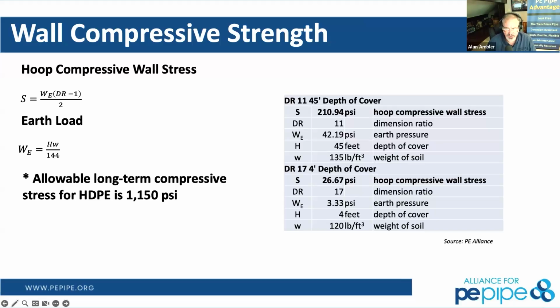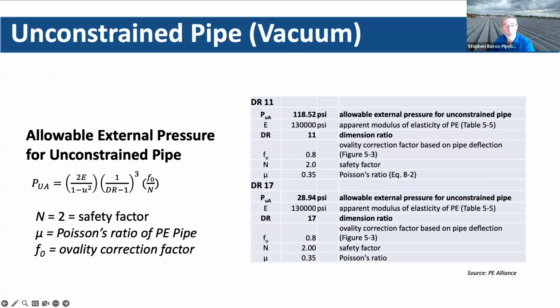Yes, Peter or Stephen? Yeah, Alan, just on that vacuum. That's a really good point, especially looking at force main design and things like that, which could go under vacuum if your vacuum relief valves fail or something like that. Even with a DR17, your allowable external pressure could be almost full vacuum without collapse, though of course it depends on your soil envelope, things like that. So you're not going to have to worry about this type of full vacuum effect if your vacuum relief valves do fail in a force main. It's not going to damage the polyethylene unless you have much thinner walls, DR21, DR26, things like that, which are normally for gravity. Absolutely, Stephen.